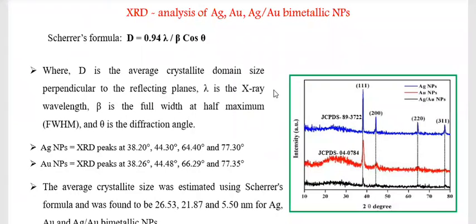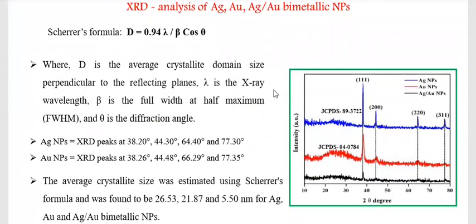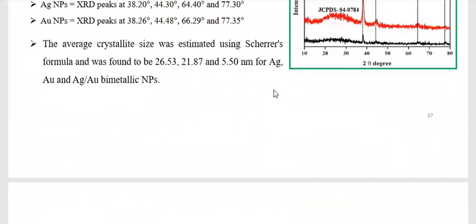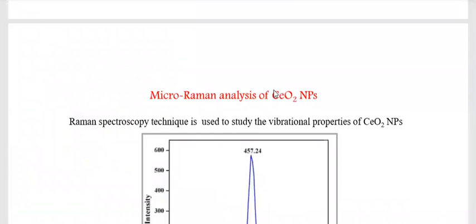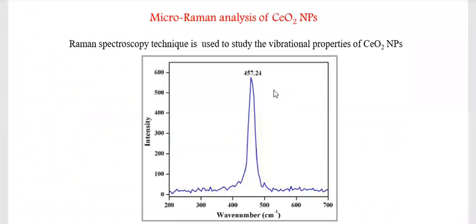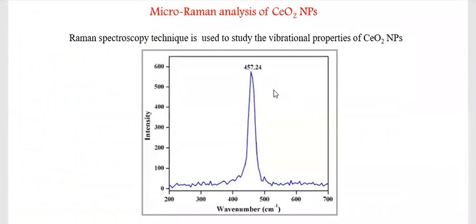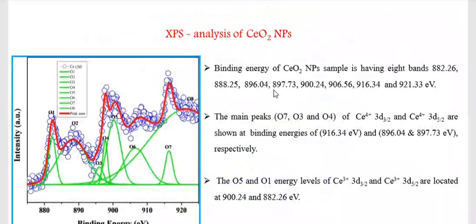Micro-Raman analysis: the peak at 457.24 is the F2g vibration for cerium oxide, which confirms the cerium oxide nanoparticle. XPS determines the valency and oxidation state. It shows that the oxygen bond confirms the presence of Ce 3+ 3d 3/2 and 900.24 and 882.26 Ce 3+ 3d 5/2, respectively.